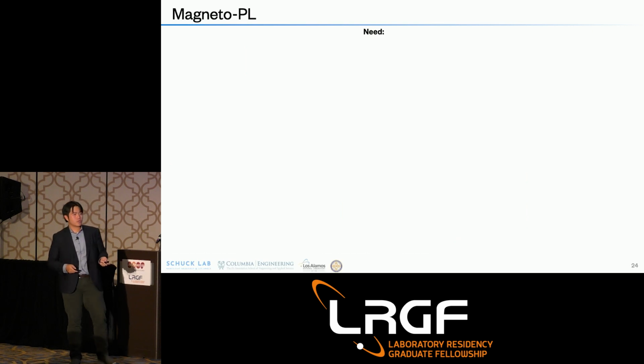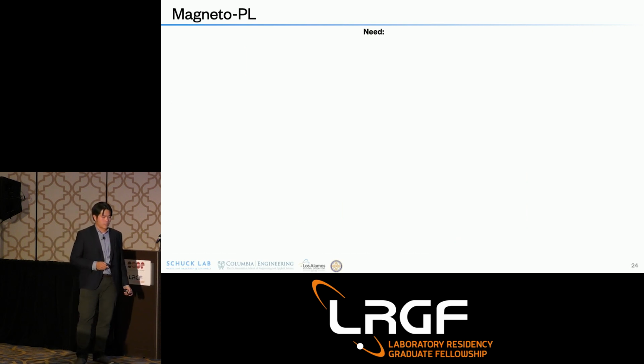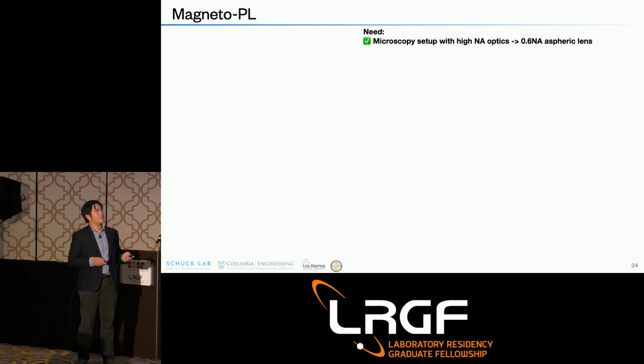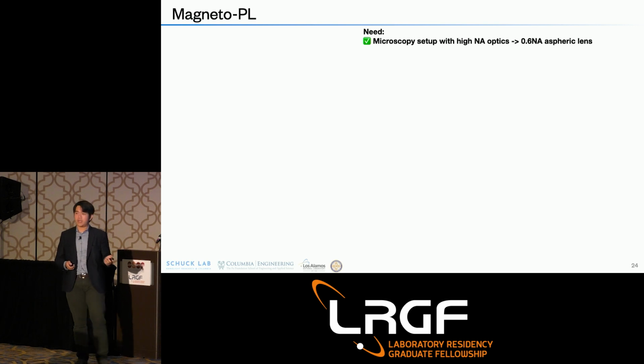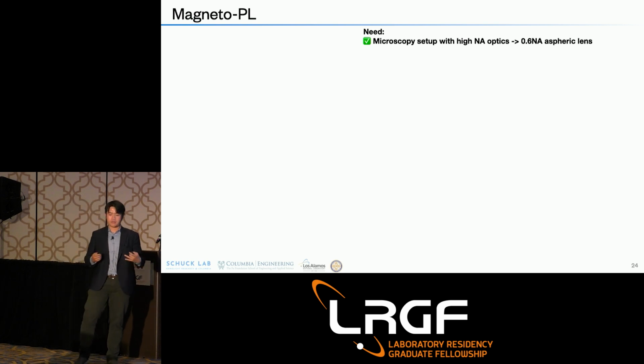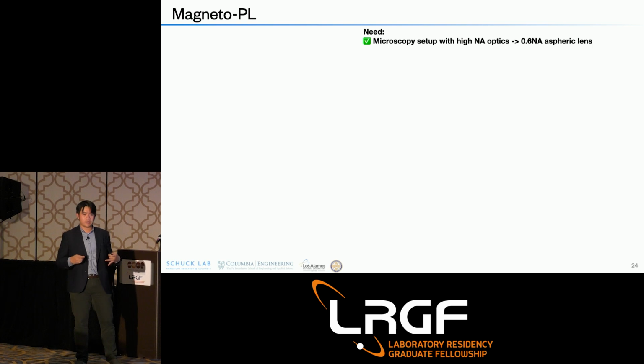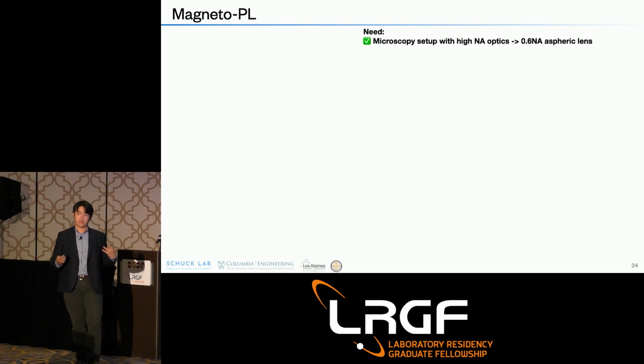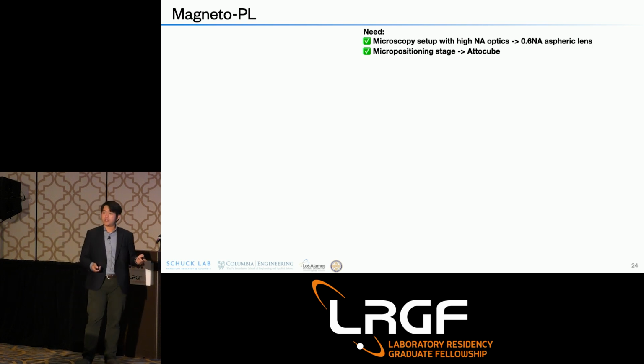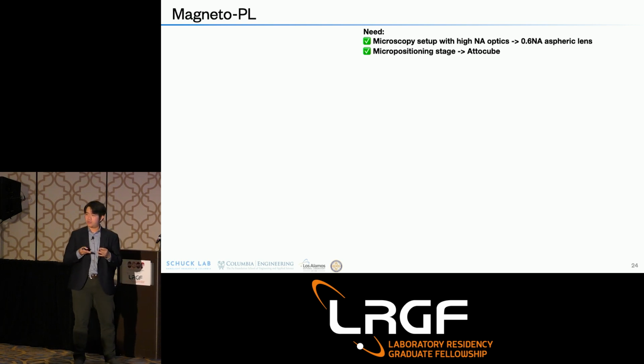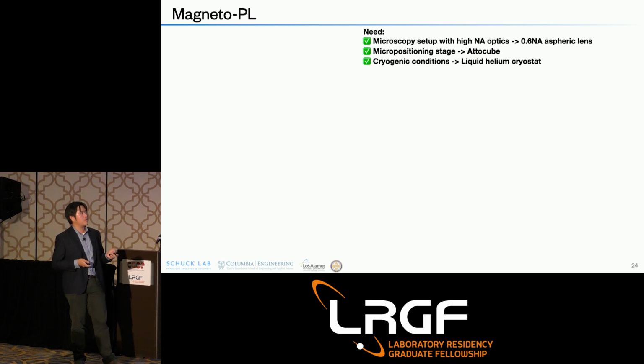Now, if you go back a step, you can see that the need for this project can really get a little bit out of hand, but I can highlight this real quickly. One is that we need a microscopy setup with high NA optics. High numerical aperture allows us to collect grazing angle emission. Collecting all the photons emitted from this nanoparticle is very important. We need an attocube stage, allowing us to position the sample such that we're getting a tight focus and there's no deviation from the focus spot itself.